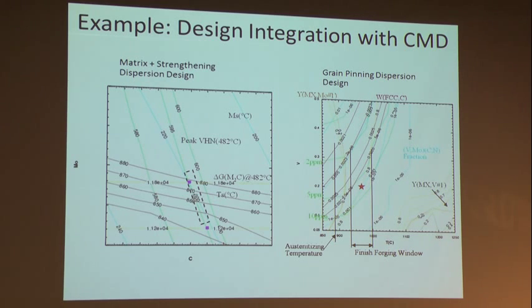The way that's all put together is by this type of parametric design. Here's an example for the stainless landing gear steel of a cross plot for a couple of composition variables of the parameters important to the strengthening efficiency. The thermodynamic driving force shown by the yellow contours is important to controlling the particle size, and then that in combination with the phase fraction determined by the carbon content leads to these predictions of the peak hardness we can achieve in tempering such a steel.